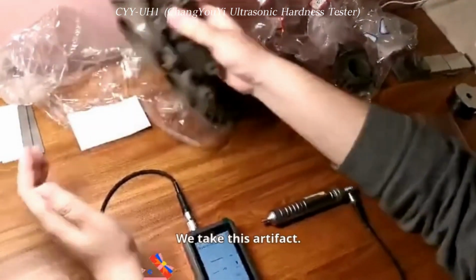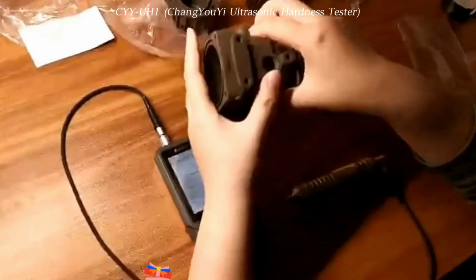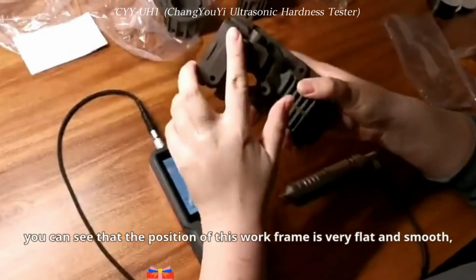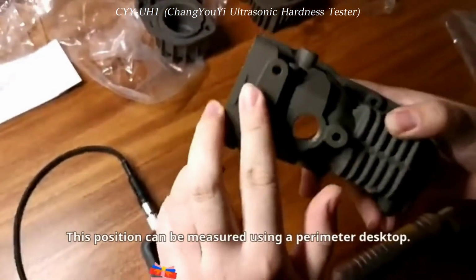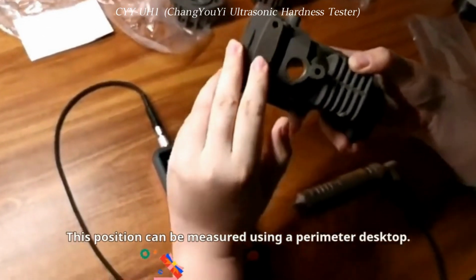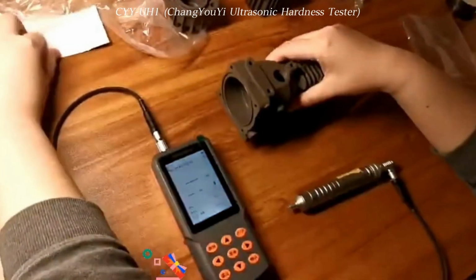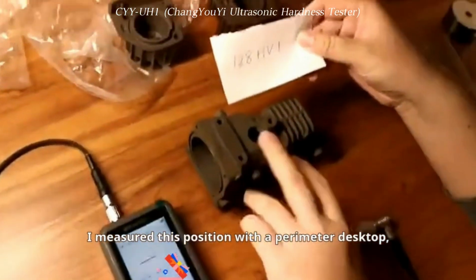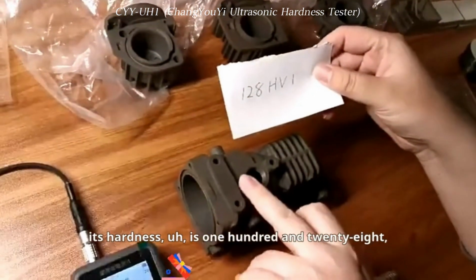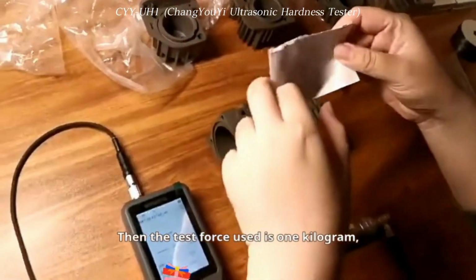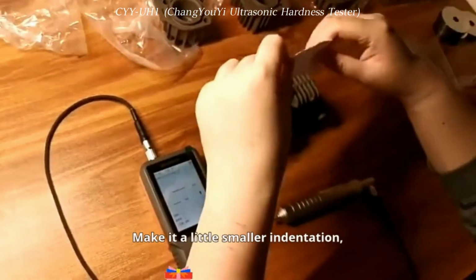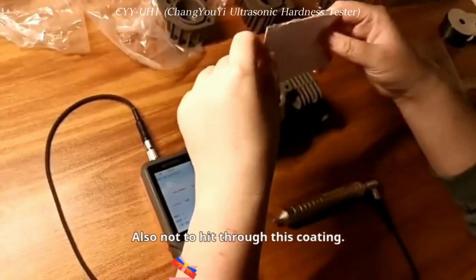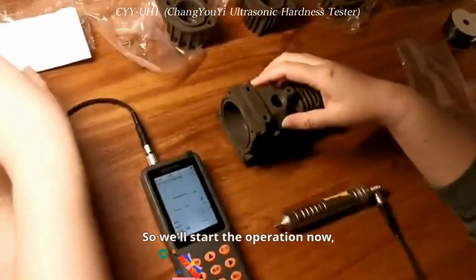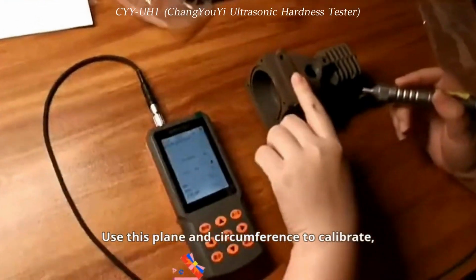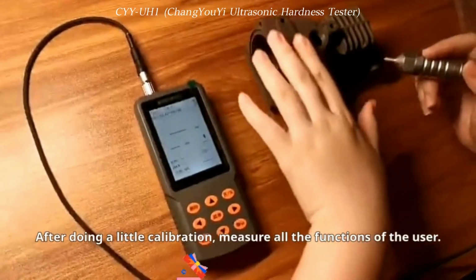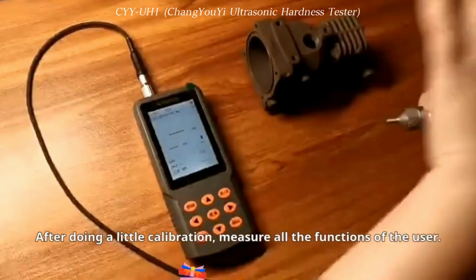First of all, we take this workpiece. You can see that the position of this workpiece is very flat and smooth. This position can be measured using a desktop tester. Today, I measured this position with a desktop tester. Its hardness is 128, and the test force used is 1 kilogram, to make a small indentation and also not punch through this coating. So we'll start the operation now. Use this plane to calibrate. After doing the single-point calibration, measure all the user's workpieces.